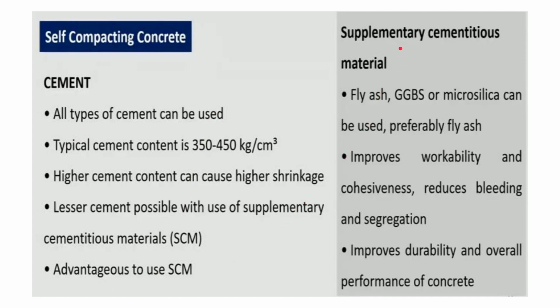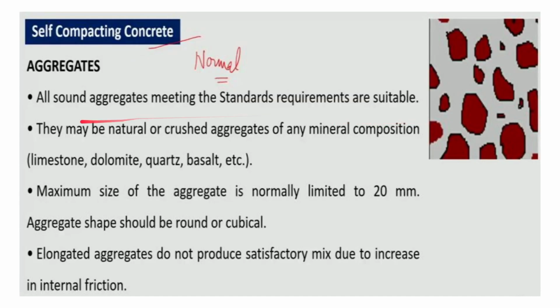What are the various types of supplementary cementitious materials? They are basically fly ash, GGBFS, microsilica, etc. It has been found that fly ash can be used preferably, because there are a lot of thermal power plants, so we can easily avail it. It improves workability and cohesiveness, and reduces bleeding, the release of water to the top, and also segregation. So it improves durability and the overall performance of concrete. That is all about cement.